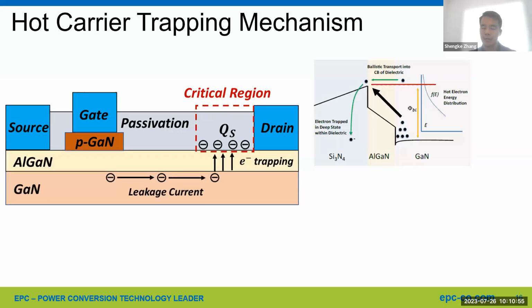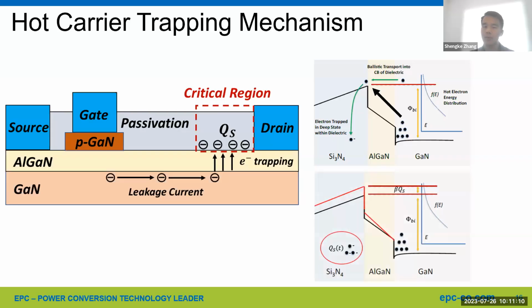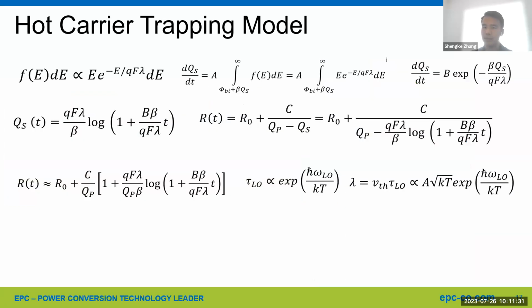The majority of electrons do not have sufficient kinetic energy to get over the barrier. Only a very small fraction of electrons does, and then subsequently get trapped within the silicon nitride dielectric layer. As more and more electrons are trapped, the barrier height is further enhanced by the electrostatic field resulting from the trapped charges, as indicated by this arrow. This dynamic barrier height change is essentially the key for the lifetime model development.